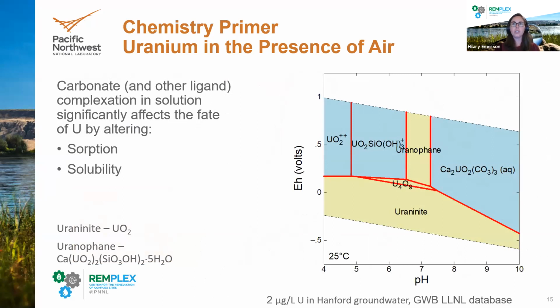And so next, I wanted to show another Pourbaix diagram, but this one takes into account the major constituents in groundwater at the Hanford site as an example. And some of those constituents include carbonate, calcium, and silica. And as you can see here, this significantly changes the speciation of uranium, and we can see that we're forming these calcium uranyl carbonate species in the alkaline pH range, and then starting to form some mineral phases too, depending on the concentration of uranium in groundwater.